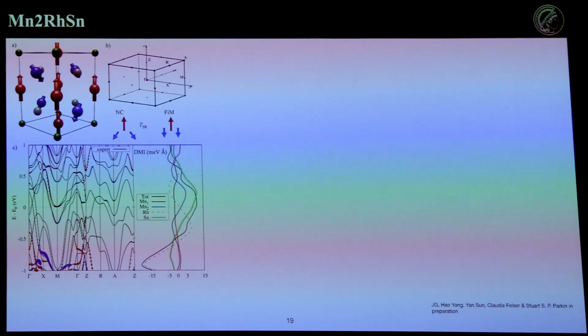So yeah, the first compound is Mn2RhSn. Here's the band structure, spaghetti plot, not so interesting. What's actually more interesting is the DMI in this system. Now, as we said earlier, the DMI comes from platinum. You know, platinum and these 5d elements have all the spin-orbit coupling. But now as you look at this Berry curvature as a function of energy, at the Fermi energy, the DMI is mostly coming from this green case, which is Sn, which seems very strange. It's like a p orbital giving you DMI. But it's because these p orbitals do have spin-orbit coupling, and they're also much more extended than the d elements. And as I said, you have this Jahn-Teller distortion, which puts all the d states down. So if you can shift your Fermi energy here, then you can get a larger DMI due to your 5d elements, okay? But yeah, that's the case.